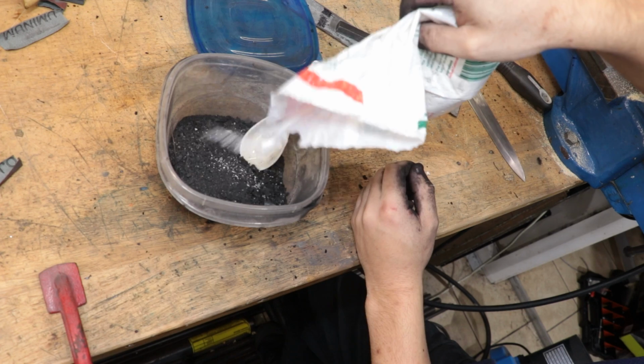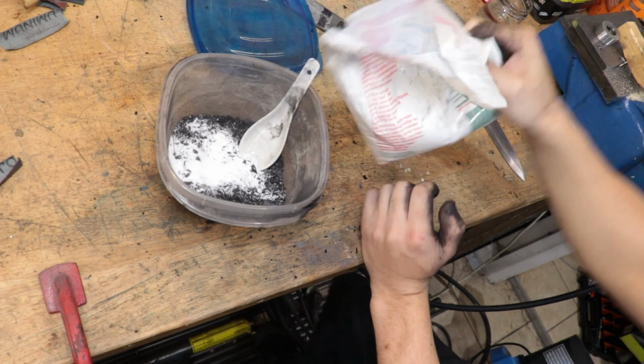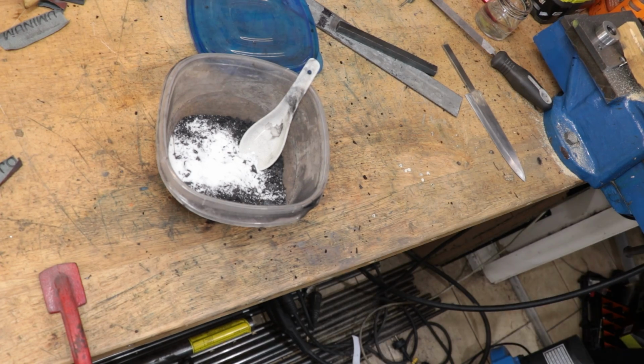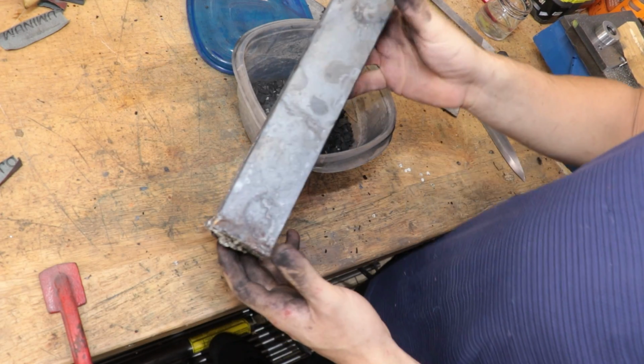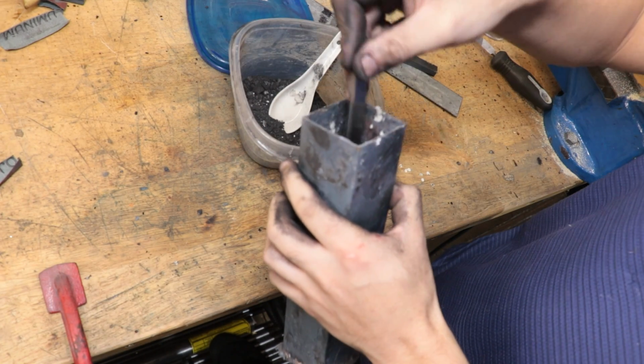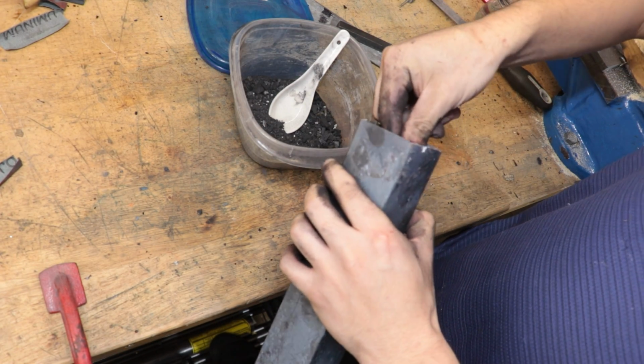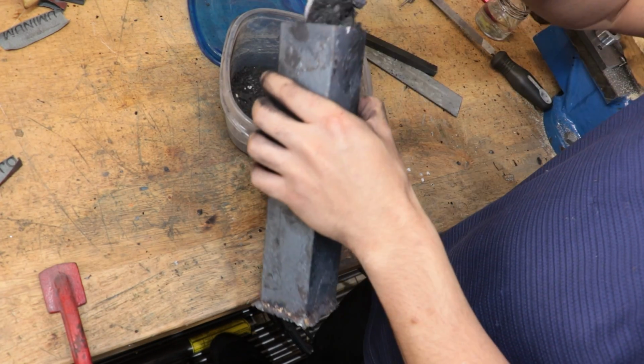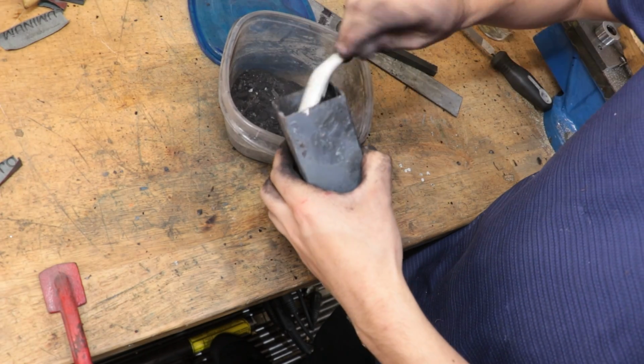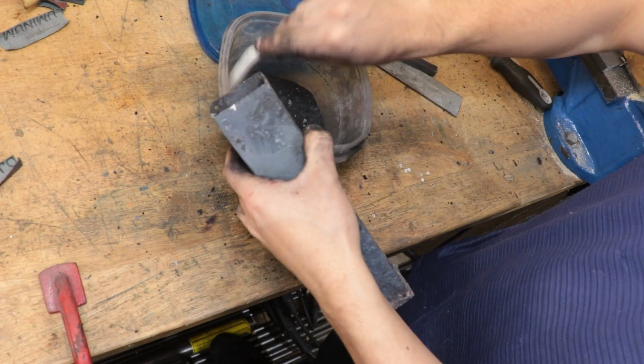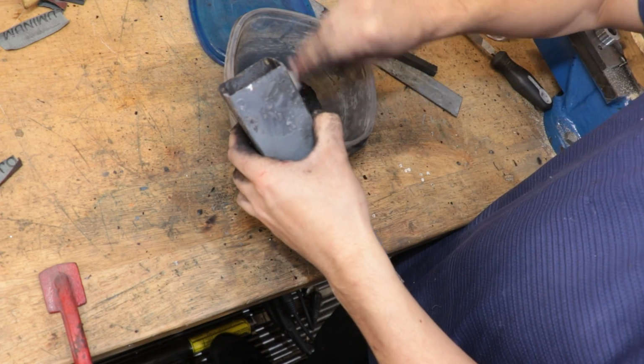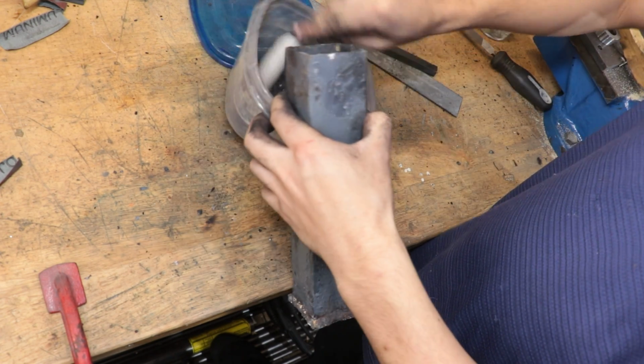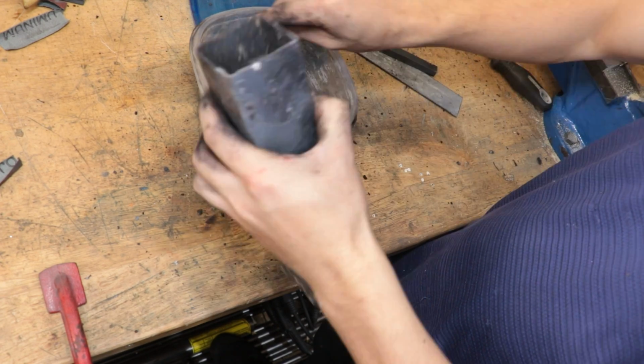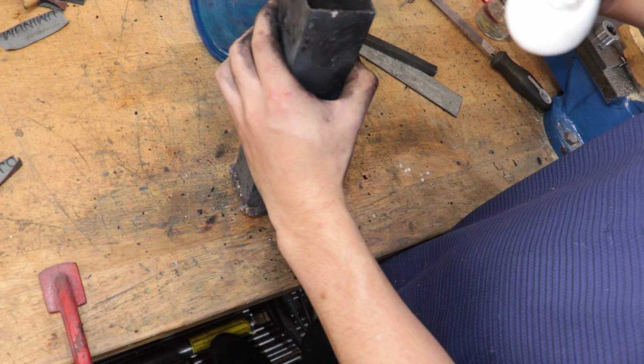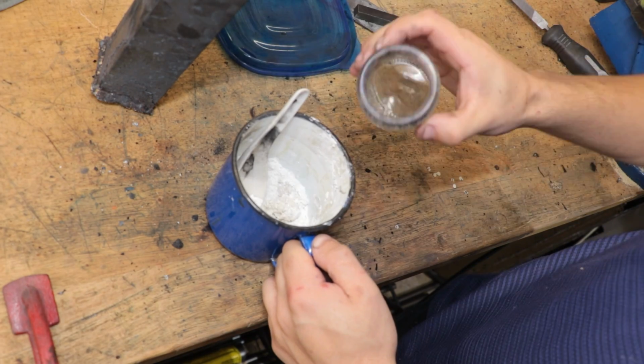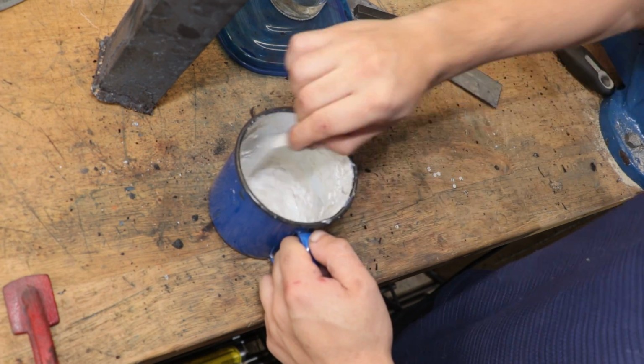I have a dedicated video on the subject, but in short, the piece of steel is going to be placed in a steel packing box. It's effectively a piece of tube with the bottom welded up. I'll place the knife into the box and then I'll pack it in with a mixture of crushed up charcoal and sodium carbonate. The charcoal is going to be our main source of carbon, although the sodium carbonate does help in the early stages. Some people do add barium carbonate, and there are a few other things which you can add, but I think sodium carbonate is a good addition because it's very cheap and you can buy it as washing powder. I can then seal the top off with a heat-proof plaster or cement, and then I can get it in the furnace.